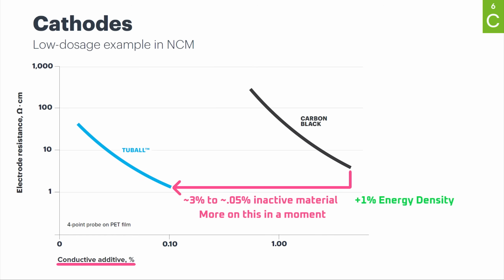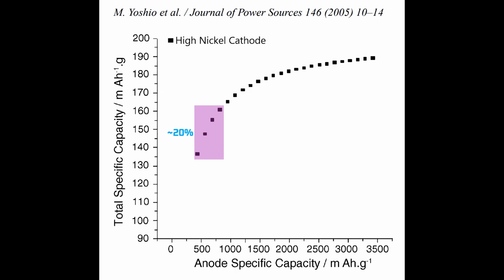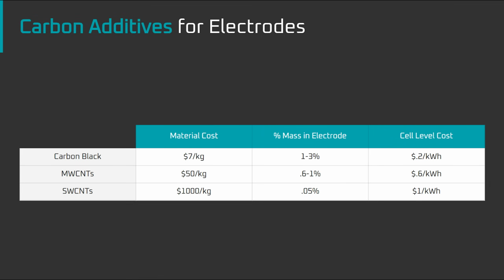Third, by replacing the 2 to 3% carbon black that's used in conventional electrodes with a fraction of a percent of nanotubes, the dead weight that's removed could increase the energy density of the battery cells by about 1% or so. That is, there would be benefits to using single-wall carbon nanotubes in conventional chemistries, but most of the benefit of nanotubes would come from unlocking the potential of higher silicon battery cells, with up to 20% greater energy density over time. Let's move on to cost.